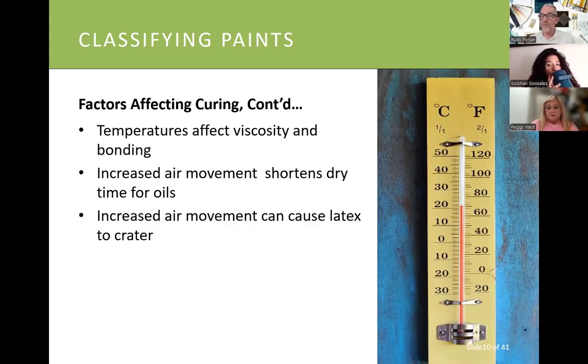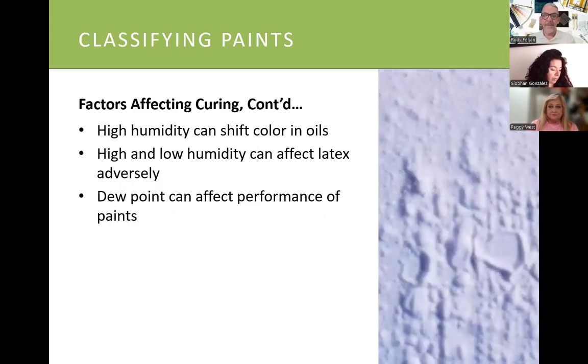So you see more brush marks and so forth when you're spraying, especially with oil-based paints, and I've seen it with latex as well. If there's too much air movement, a lot of times you get these little bubbles appearing, and those tend to float out. But if they dry too fast, then you get these little bubbles that look like craters, like craters of the moon on your coating, and that's generally because the coating is drying too fast. So you have to keep that in mind.